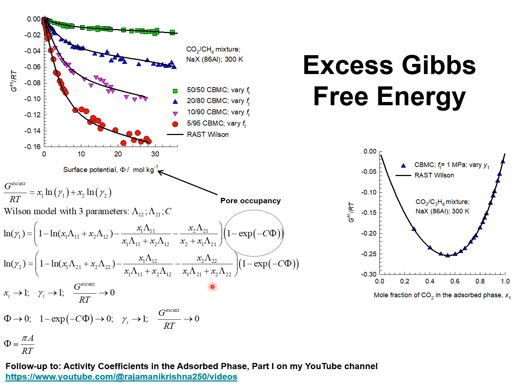In setting up, say, the Wilson model to describe the activity coefficients in the adsorbed phase, we have to introduce a correction factor indicated here, which is 1 minus exponent of minus C, a constant, times phi, the surface potential. This correction factor is a quantification of the pore occupancy.